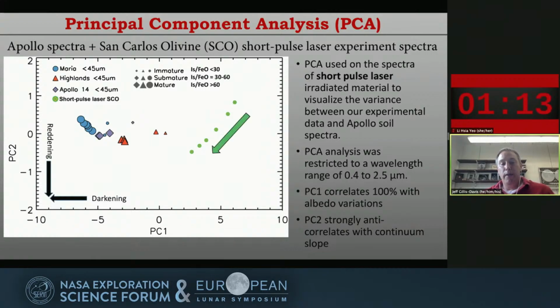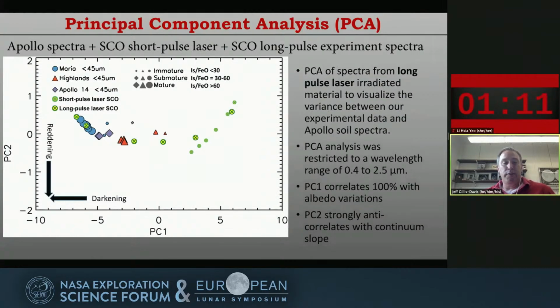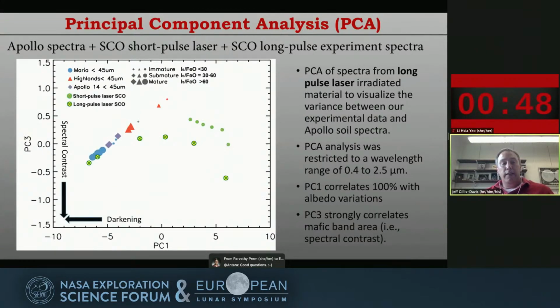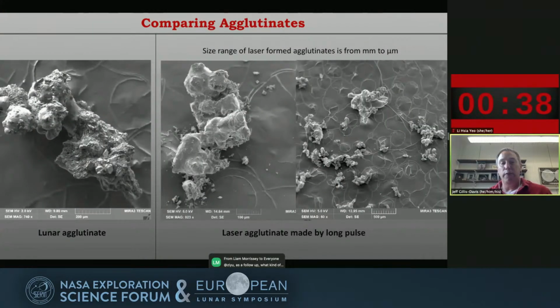Now we'll pop up the long pulse laser. These yellow-green circles are the long pulse laser results. You can see that we are now capable of getting into the same field in the PC space for PC1 and PC2 compared to fresh and mature lunar materials, but particularly Mare materials. This is also showing with PC3 and PC1, where PC3 here is spectral contrast, so loss of spectral features. Again, we're seeing that we match Mare material very well.